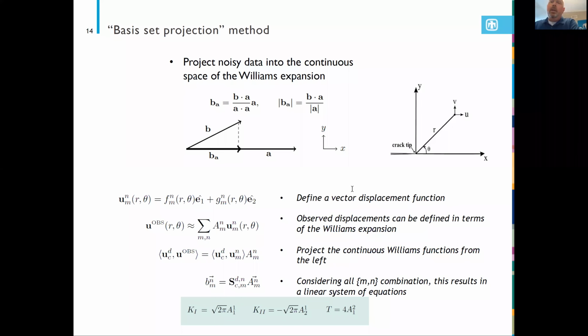From there, we can model our observed displacements. These are all discrete. These are all evaluated at each one of the atomic positions at a given r and theta. We can model these observed displacements in terms of these continuous functions and their leading coefficients as follows. We project the continuous Williams expansions onto the observed displacements. So this would be the inner product between the discrete observed displacements and the continuous functions evaluated at each one of the ri and theta i observed displacements. This gives rise to a discrete vector.